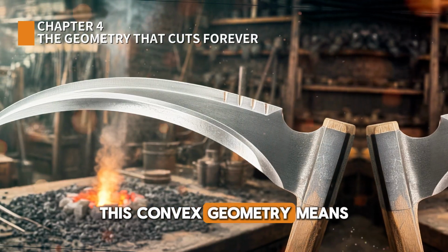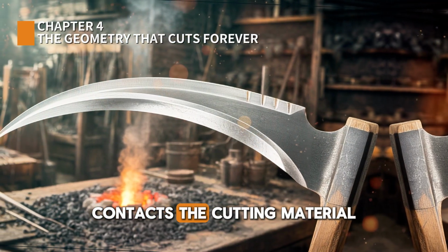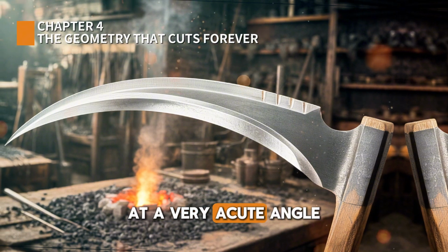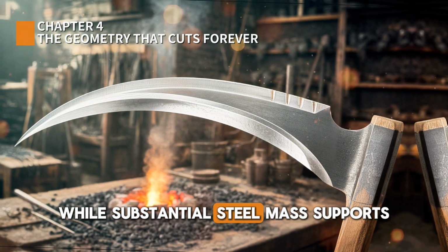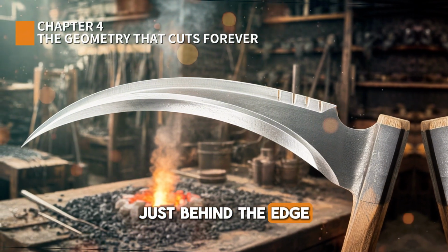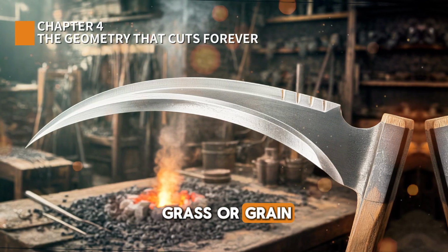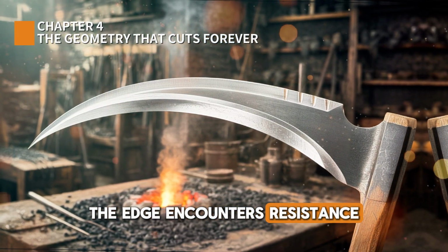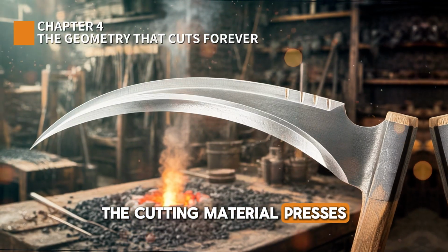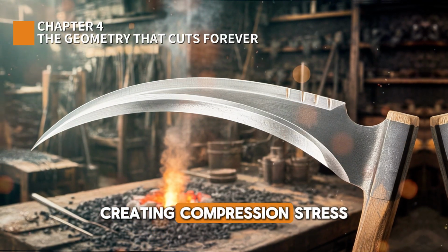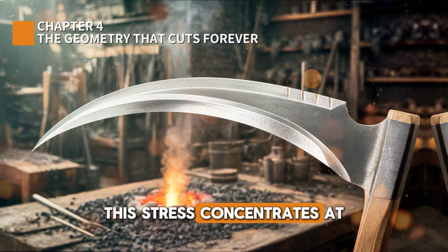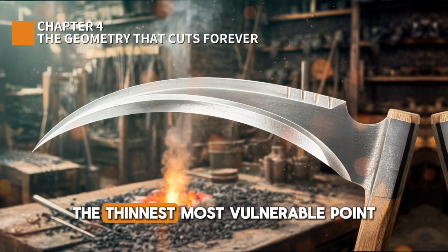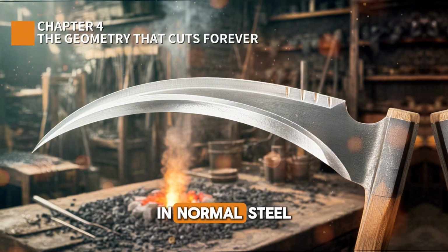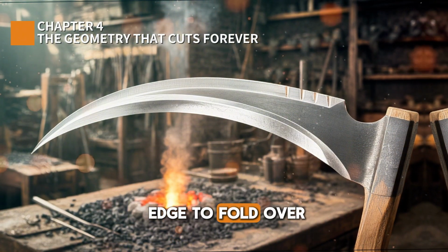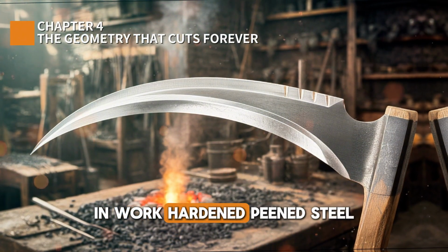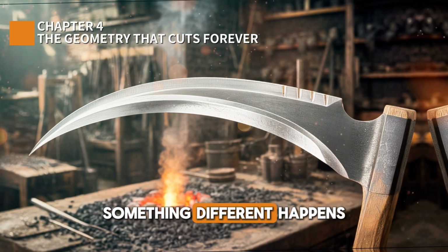This convex geometry means the edge apex contacts the cutting material at a very acute angle, while substantial steel mass supports just behind the edge. When the blade cuts grass or grain, the edge encounters resistance. The cutting material presses against the edge, creating compression stress. This stress concentrates at the edge apex, the thinnest, most vulnerable point. In normal steel, this would cause the edge to fold over or chip. In work-hardened peened steel, something different happens.